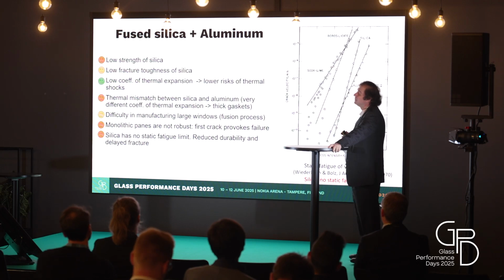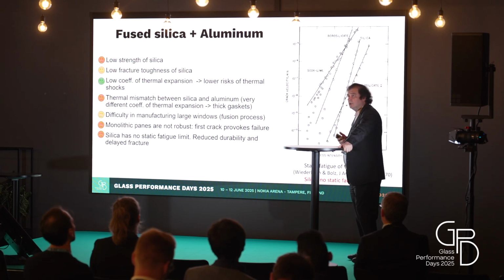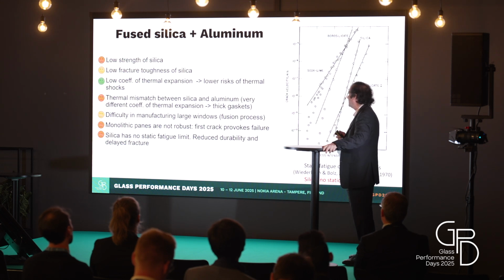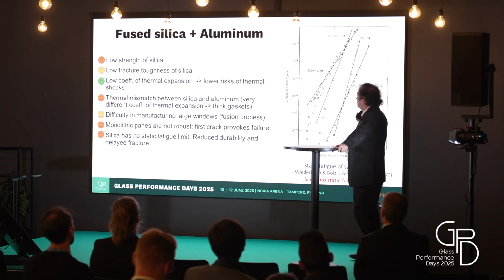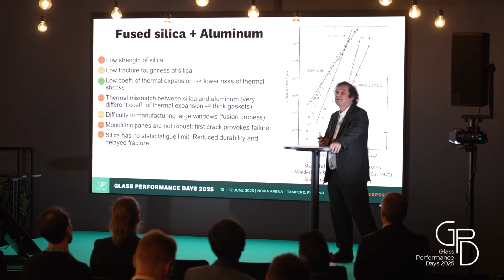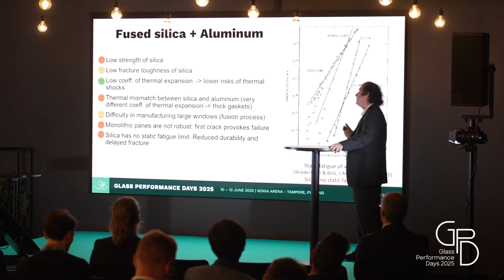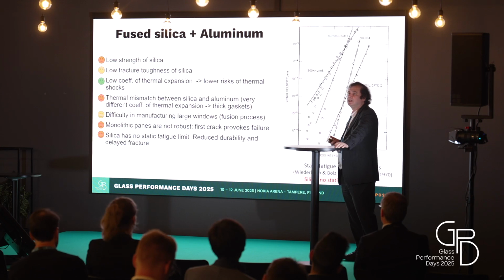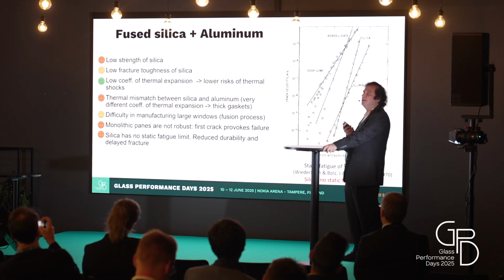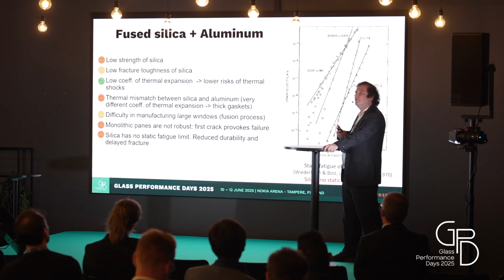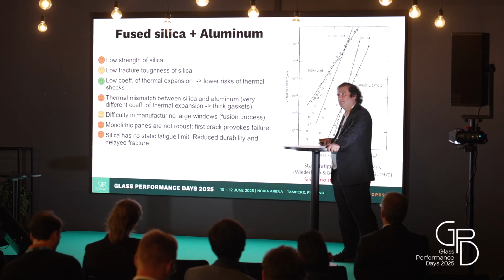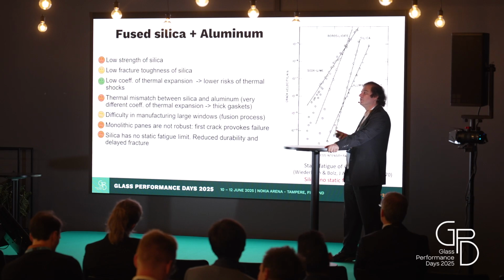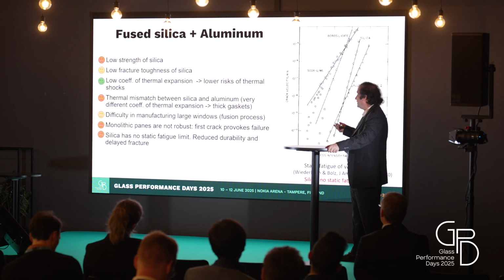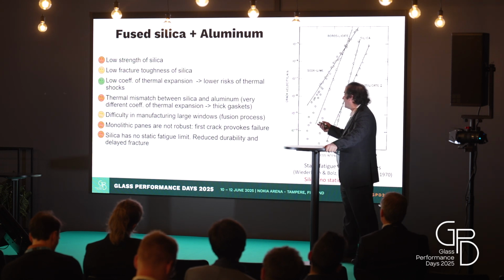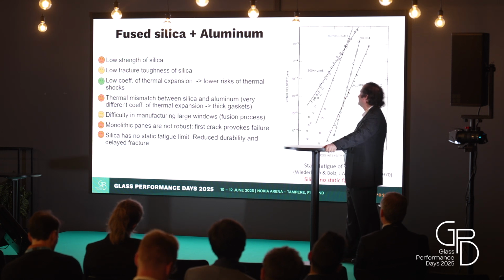Then there is a difficulty in manufacturing very large windows made of fused silica. It is very expensive, and most of all, fused silica does not have a static fatigue limit. This means that in theory, even if this time could be very long, whatever the applied load, there is a time at which the material will fail because of slow crack propagation. We take this into account also in ordinary glass, but for fused silica it is a very important issue.